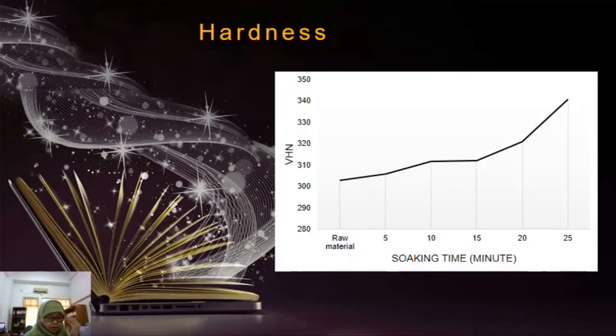The second is hardness. The hardness test results showed that the FeCrMn alloy had a hardness of 302.8 Vickers hardness. The cryogenic process with 5 minutes immersion showed a minimal increase in hardness, but this hardness continued to increase until 25 minutes immersion. A tiny increase at relatively short immersion time is due to the absence of a crystal structure change, but with the longer the immersion time, the hardness value continues to increase. This is due to the arrangement of austenitic and carbide grains.